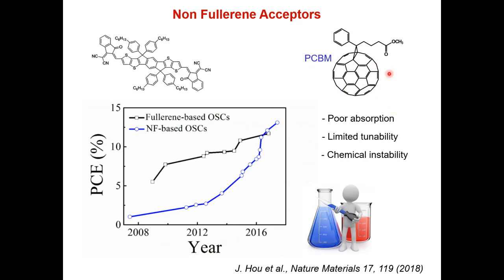And then people started to realize, a few years ago, that PCBM in the end is really not the best candidate. First, it's poorly absorbing where the sun is emitting. And it's very difficult to do some chemistry on this ball to tune the LUMO energy, which is quite useful for optimization. And with light, this ball is also unstable and can dimerize and make complex molecules that are not useful for the application.